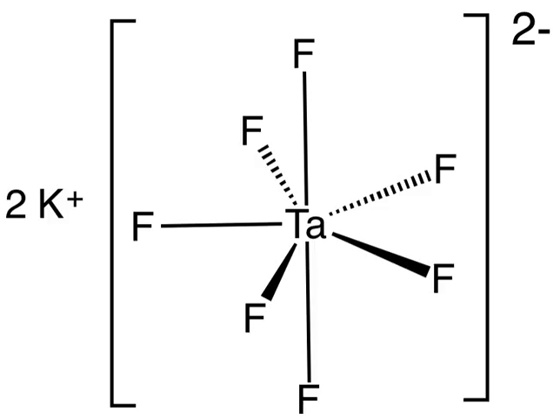At temperatures above 230 degrees Celsius this converts to β-K2TaF7, which is orthorhombic. This structure also consists of potassium ions and the complex anion. The structure of the seven-coordinate TaF7^2- units is essentially unchanged. However the potassium atoms now exist in two environments where they coordinate to either 11 or 8 fluorine atoms.